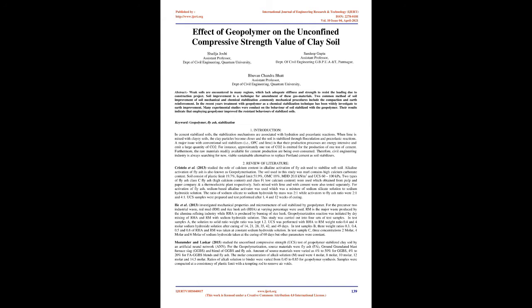2. Review of literature. Cristello et al., 2013, studied the role of calcium content in alkaline activation of fly ash used to stabilize soft soil. Alkaline activation of fly ash is also known as geopolymerization. The soil used in this study was marl, which contains high calcium carbonate content. The soil has a plastic limit of 19.7%, liquid limit 51.9%, OMC 18%, MDD 20.8 kN per cubic meter, and UCS 60